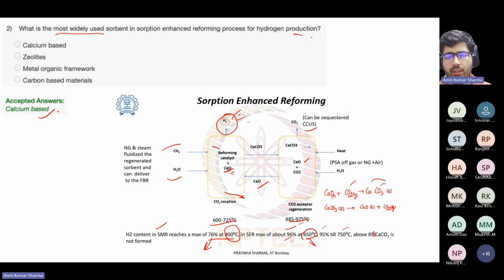95% till 750 degrees, and above 850 calcium carbonate is not formed. So it will not work above 850 degrees centigrade, because this reaction will not work above 850 degrees centigrade. So this is about the sorption enhanced reforming, and the widely used sorbent is calcium based.